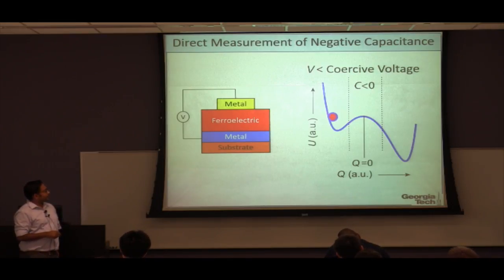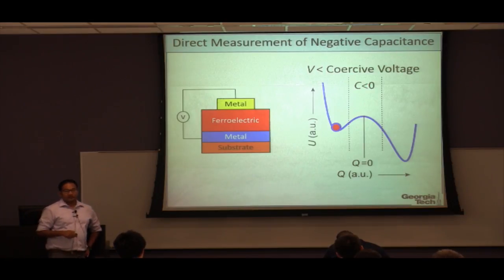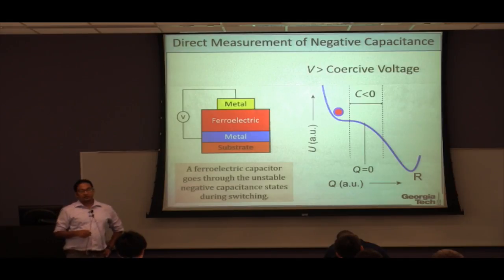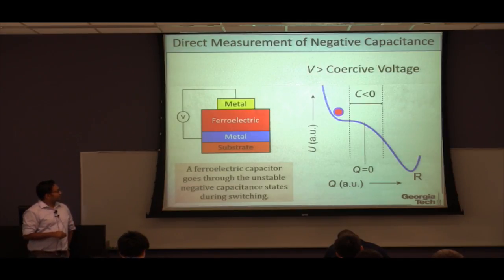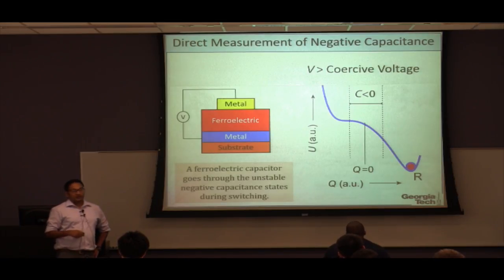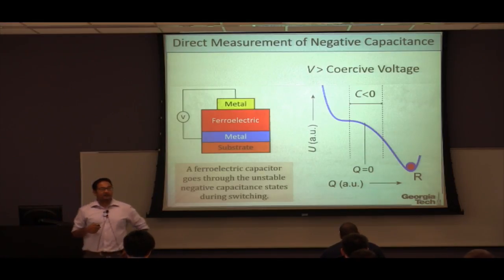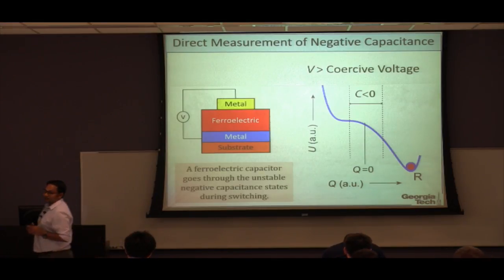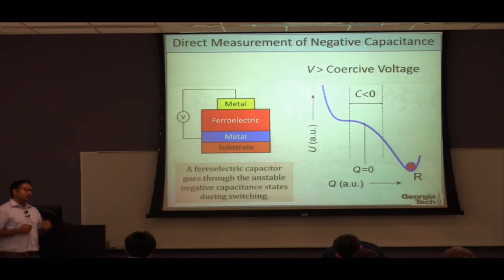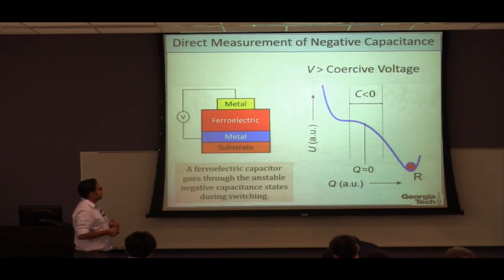So what will happen is that the polarization will fall down to the nearest minima, but it won't cross the barrier because the voltage is too small. Now, if we apply a voltage larger than the coercive voltage, the energy landscape tilts further. As a result, the polarization will roll downhill, and as it rolls downhill, it actually goes through the negative capacitance region. So that really gave us the insight that by doing a time-dependent measurement, we might be able to do a direct measurement of negative capacitance.